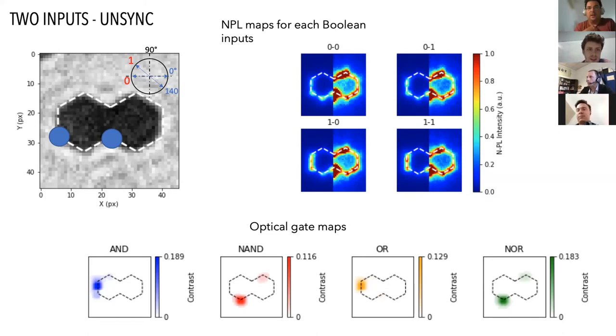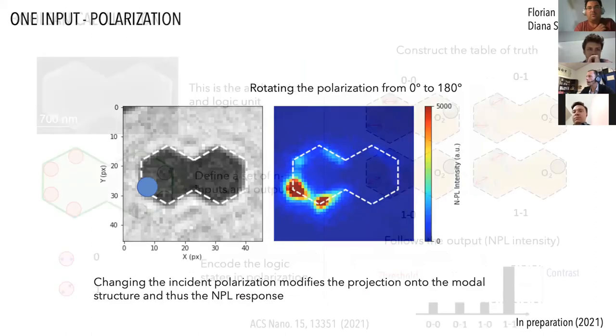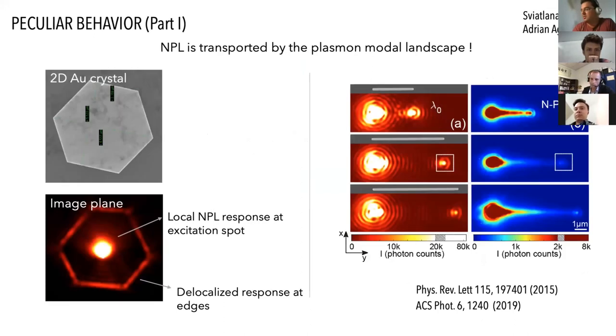Mm-hmm. And in fact, maybe the set of experiments you have could serve as a nice way to test the thermal conductivity of the electrons. We studied a couple of aspects of this, and we saw some non-trivial results with Nick Van Hulst. You can test this hypothesis and see the propagation speed, does it correlate to thermal conductivity or to the surface plasmon? You can maybe explain the NPL results, the slow response that you emphasized a couple of times. So I think that would be very interesting.